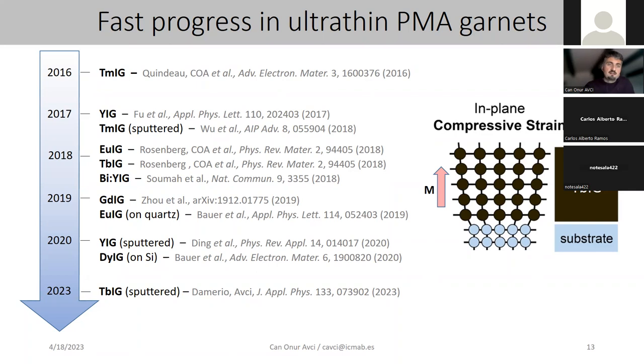Starting with the earlier work that we have done at MIT in 2016, there has been a broad interest and also effort in making these ultra-thin films of different rare earth iron garnets, all of them with perpendicular anisotropy and also with different deposition techniques. Most of the time, unless I mention anything, it's pulsed laser deposition, but there are also some efforts to produce these films by magnetron sputtering, which is important because usually pulsed laser deposition is relatively slow and generates films on a small surface area. But if you can produce these films with magnetron sputtering, it's an added value, an advantage for industrial applications, if any, in the future.